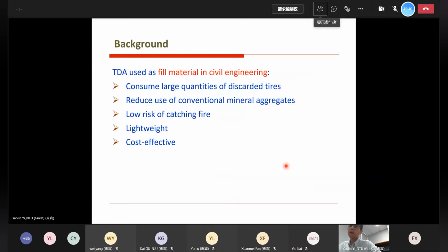The advantage of this application is that this is not new, but there are still some advantages. The first one, it can consume large quantities of discarded tires, and it can also reduce the use of conventional mineral aggregates. There is a very low risk of catching fire, because when used in this application, we bury the tires underground. And also for civil engineering, the TDA is lightweight, because the unit weight or specific gravity is around one-third to half of the conventional aggregate. It can be cost effective because it's made from waste materials. But of course, it depends on the location. If the transportation is too far away, it's not that cost effective.